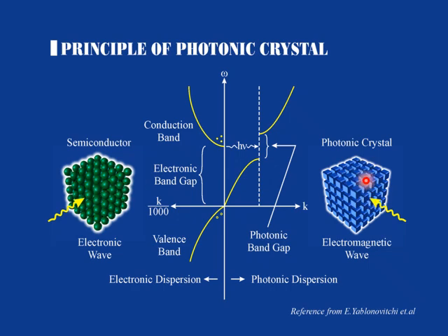And of course, in photonic crystals, imitating the semiconductors, the periodic structure of the material can reflect the electromagnetic wave by Bragg diffraction, and the photonic band gap opens in the electromagnetic wave transmission spectrum. If you introduce a structural defect, you can control the electromagnetic wave transmission and create a localized mode in the band gap. So the logic is similar between photonic crystals and natural semiconductor crystals.